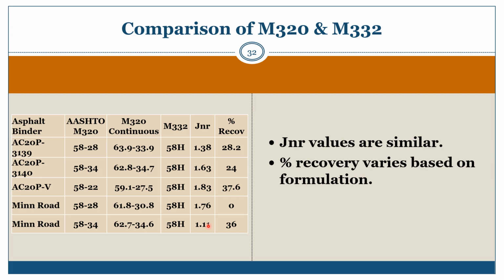So there are differences, and you have to understand that when you look at how you specify these materials, and recognize that and include it in your approach to specifying the materials. And you can see here again very different percent recoveries, from 0 up to 37, and again that's very much based on the base asphalt, the type of polymer, and the processing that was used. And I can tell you these binders came from different parts of the country, with different base asphalts and different formulations.